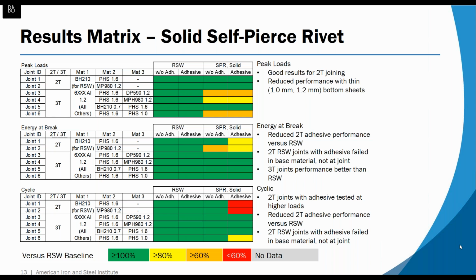Finally, in the cyclic testing, we found that without adhesive, and for the most part in the 3 thickness cases, because they didn't benefit from adhesive, the solid rivet equaled or exceeded the performance of the resistance spot weld baseline. The case where it didn't were in the two thickness joints, joints 1 and 2, with adhesive.